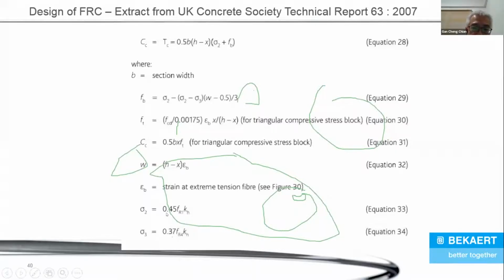And apart from being characteristic values, which is already very safe, the Concrete Society put in a reduction factor of 0.45 here for FR1 and 0.37 for FR4. Why do they do that? Because FR4 always has a bigger coefficient of variance. So the bigger the coefficient of variance, they want to put in more safety. So they only allow you to use 0.37 of the FR4. And apart from that, they put in another factor K here, and this factor K is less than 1. So you are reducing your FR1 and FR4 further. So that's why it's so important to be correct, accurate and consistent for the FR1 and FR4 values.